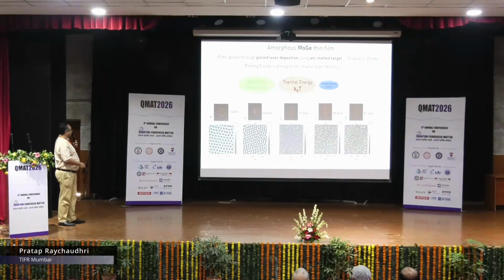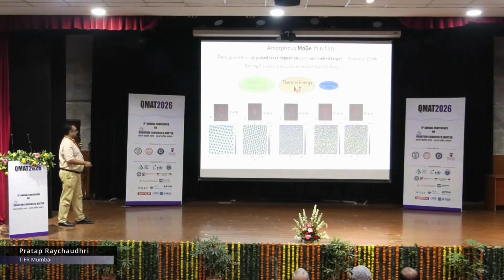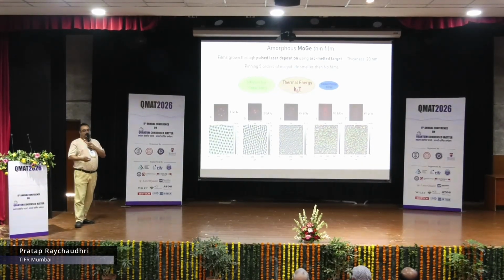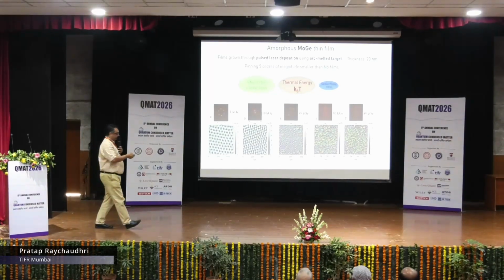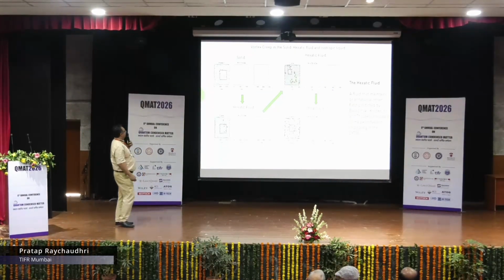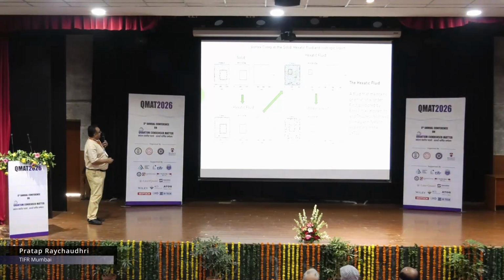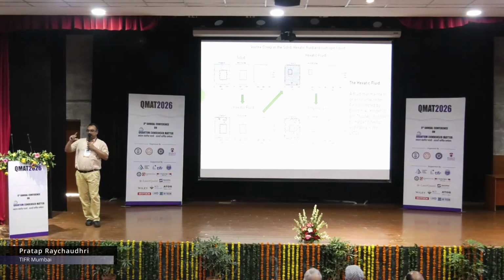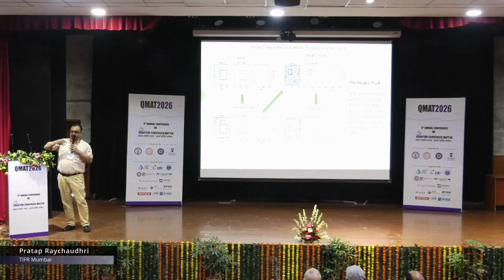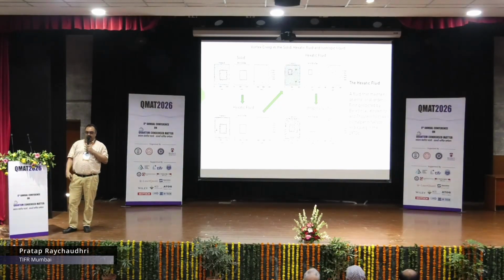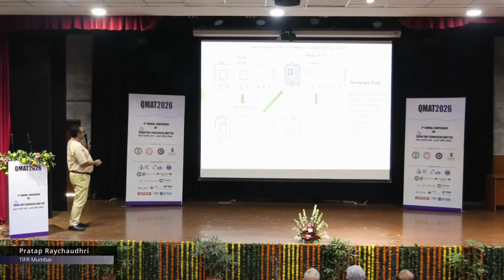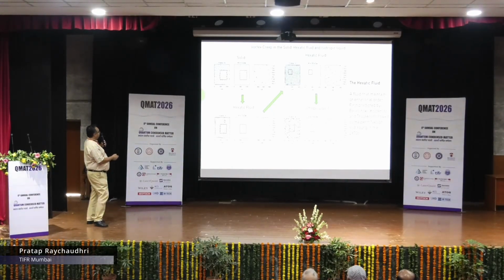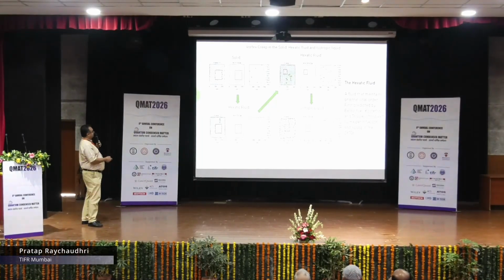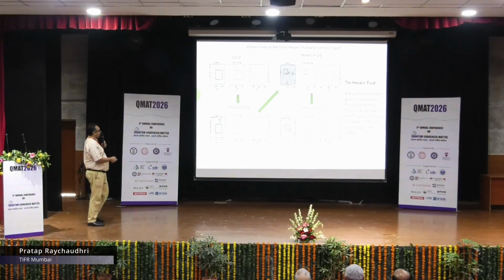At 1 kilogauss, you see a nice vortex lattice, and then as you increase field, you see more and more defects proliferating. This again does not tell you whether it's amorphous or liquid. So then we do this experiment. We take a small area, and then we keep on imaging this area continuously. We keep on taking snapshots of this area, and I join the position of the vortices to find their trajectories. So when you have a solid here at 1 kilogauss, you see that the vortex just moves a little bit about their mean position.